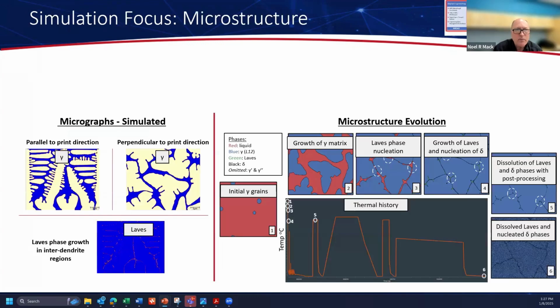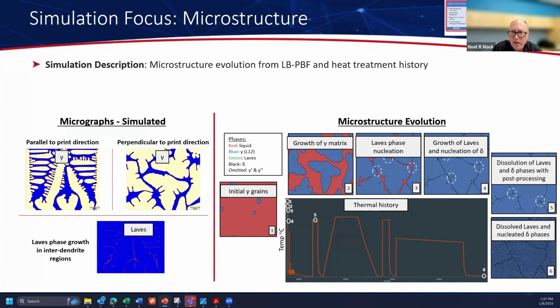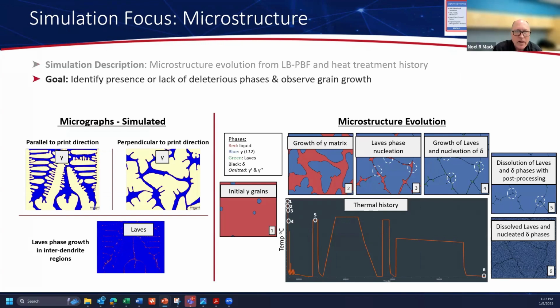So here you see the predicted microstructure evolution from the laser beam powder bed fusion process, as well as the evolution from the heat treatment history. So starting with the microstructure of the actual laser beam powder bed fusion process, and then running that through the simulation of the heat treat process. The objective here is to identify the presence or hopefully lack of deleterious phases, and also to observe the grain growth. In this case, we use the phase field code to do the simulation.